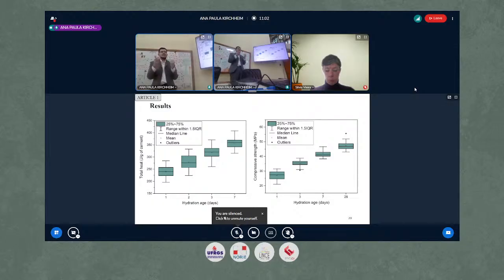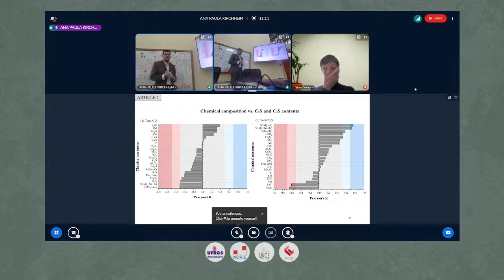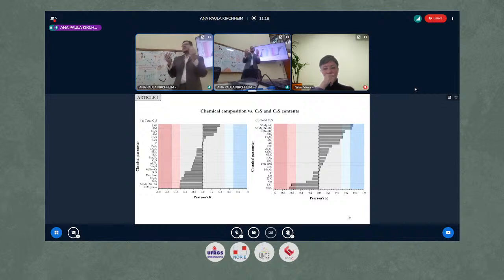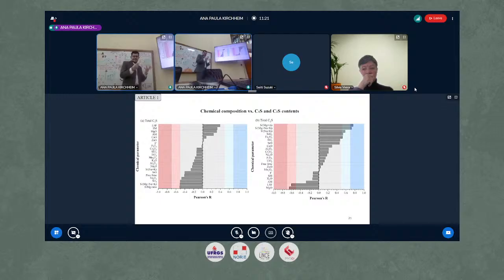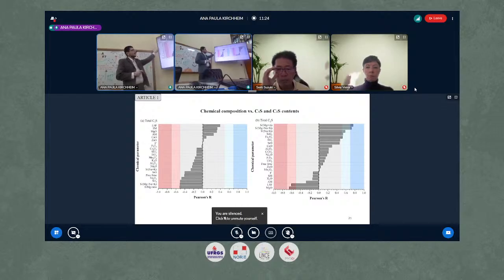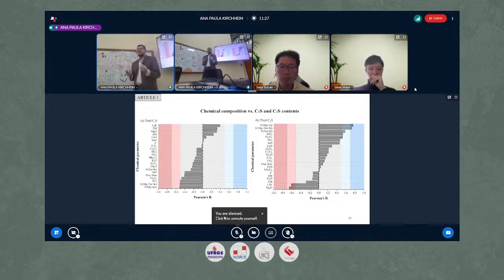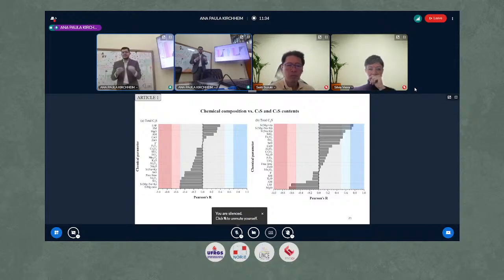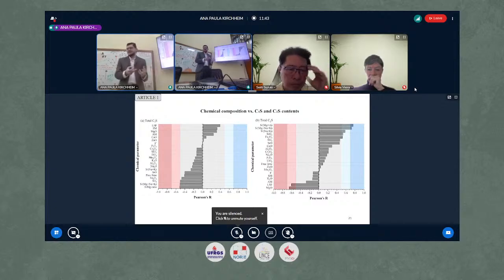And now we compare all of these results, trying to see relationships between the variables to try to explain the results. So here we use Pearson's correlation, which indicates if a variable correlates linearly or not with a property. So here we see total alite and total belite content. Obviously, if something is influencing alite positively, it is decreasing the belite. So this was as expected. Here I highlight the lime saturation factor. As expected, the higher the lime saturation factor, the higher the alite and the lower the belite.